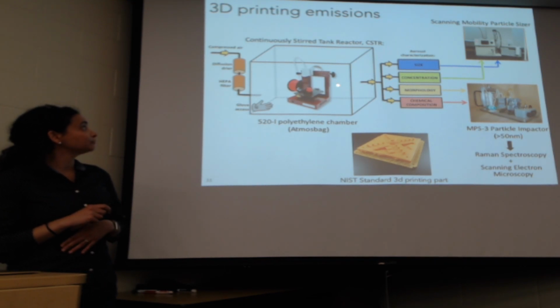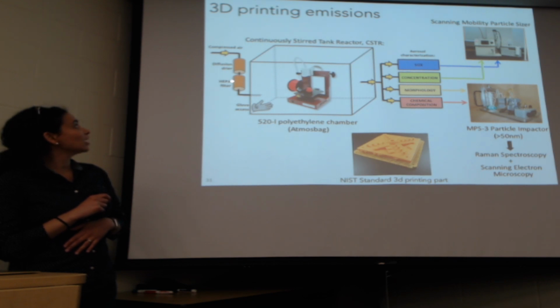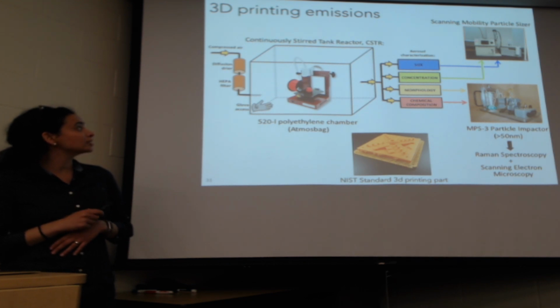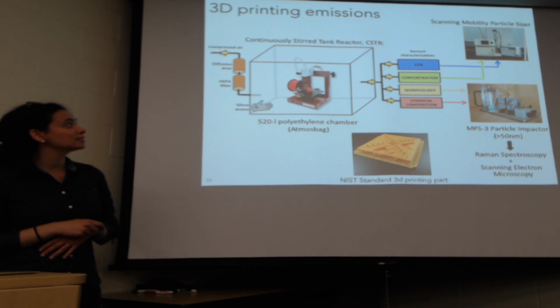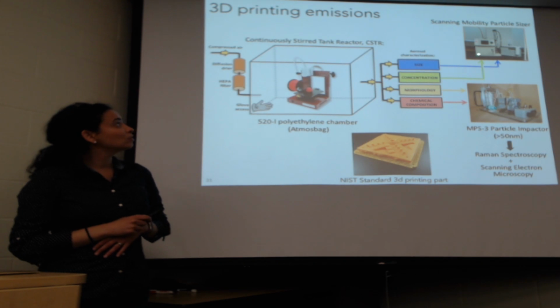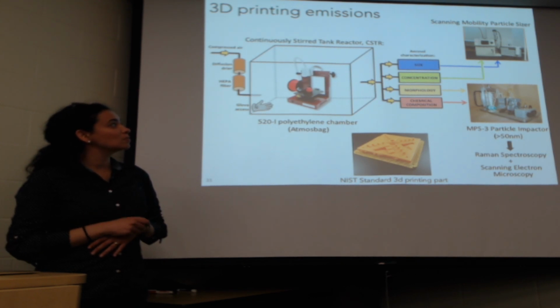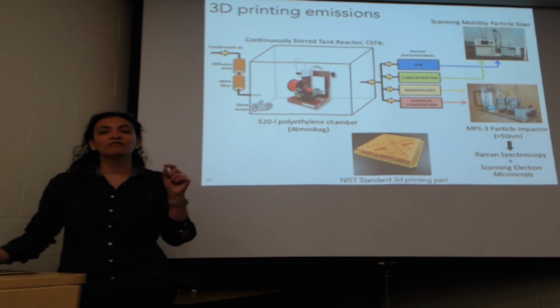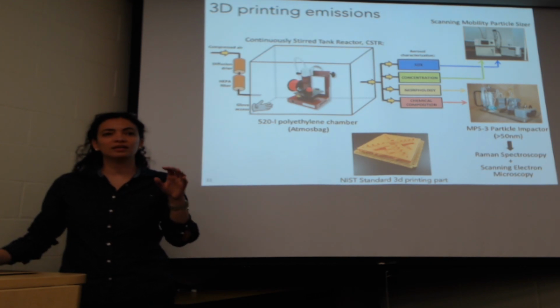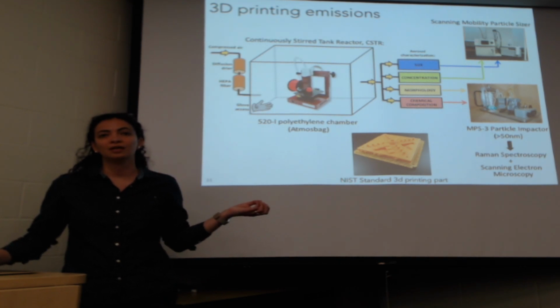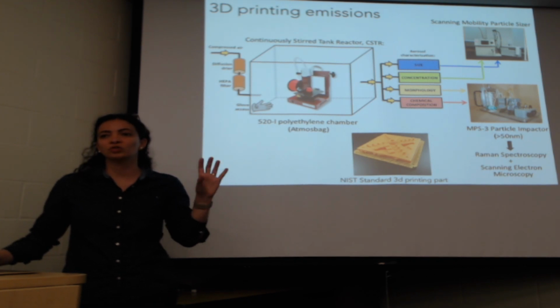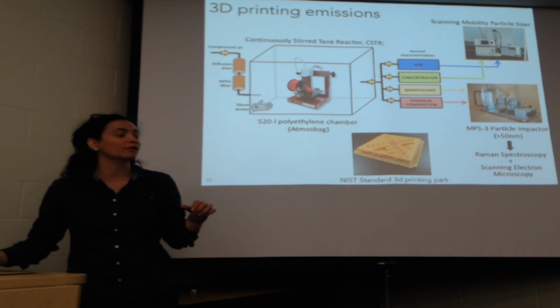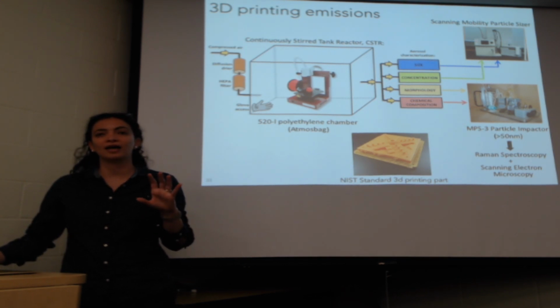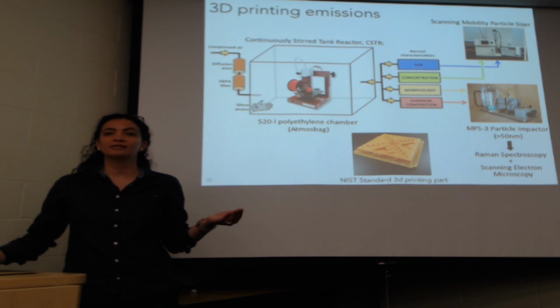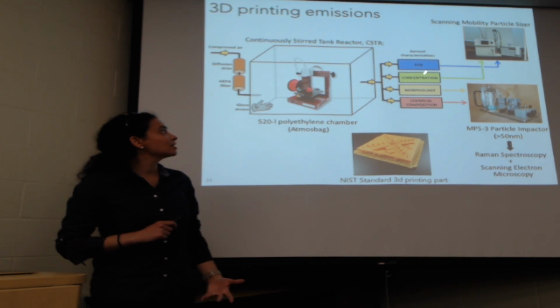Other things we did: we knew we were inputting clean air, so we had a filter to remove particles, and a dryer to remove relative humidity. We were pulling air out of the chamber at the same time with a number of instruments. The instrument on the top is the one my group uses most in the lab. It's called the Scanning Mobility Particle Sizer. That's a long name just to say that it's counting particles of different sizes. Basically it separates particles by size first, and then it counts them. It uses an electric field to do that separation. That's why it's called scanning mobility, because it's counting them by electrical mobility. What matters here is that we are counting particles and sizing them at the same time, so we can tell size and concentration.